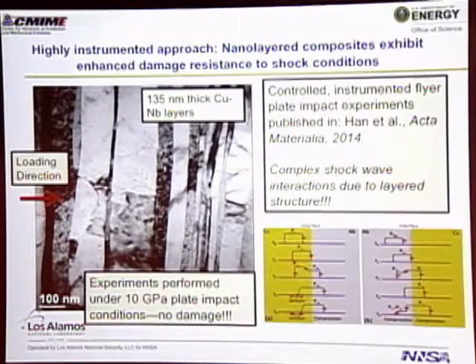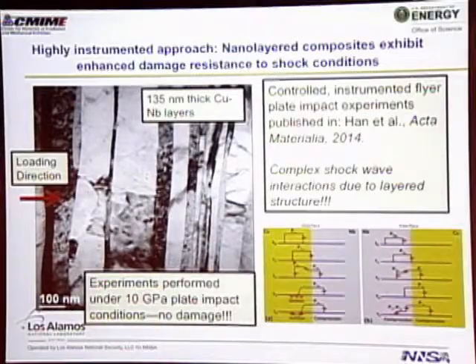So we've actually shocked these materials before. And what we found is that if we shock this with a flyer plate in a very carefully instrumented way, we can shock these to very high pressures and not see any sign of damage. It's almost indestructible at high strain rates under certain conditions. And you can take this type of data and write a very nice paper like one of our postdocs here did in Acta Materialia, and you can discuss how the complex shock wave interactions occur due to the layered structure.